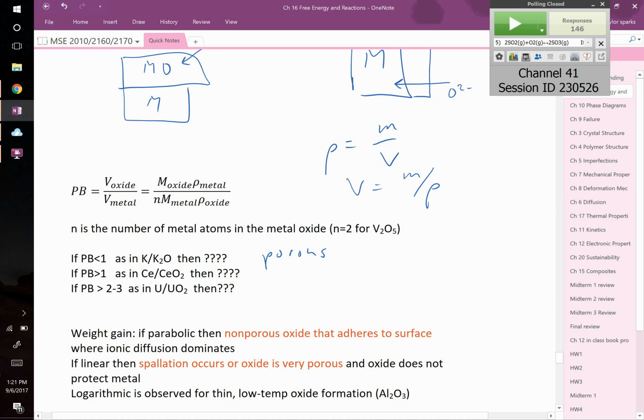If it's greater than 1, like ceria or cerium oxide, what about that? Yeah, I should say that it is greater than 1 but less than 2, right? In that case, we call those passivating, meaning it's a pretty close match, and so it's going to be relatively dense. It doesn't mean you can grow the oxide infinitely thick. It might only survive a micron thick or a few nanometers thick, depends, but it'll stay put up to a certain thickness, and in that case, it's going to be passivating.